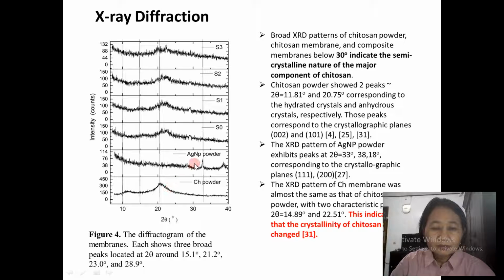The XRD pattern of the silver nanoparticle powder shows two peaks, the first at around 33 degrees, and the second one around 38.18. The XRD pattern of the CH membrane, the pure chitosan membrane, is the same as the XRD pattern of the chitosan silver nanoparticle membrane, where we found two peaks. This indicates that the crystallinity of chitosan did not change.